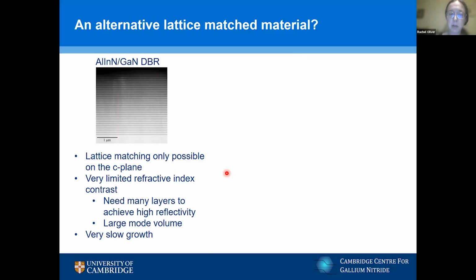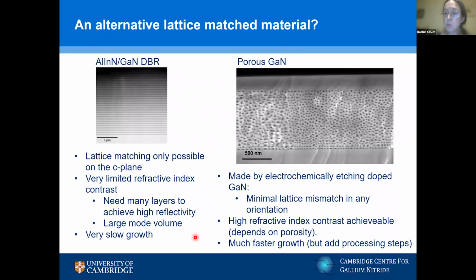The other problem with aluminium indium nitride, gallium nitride, is that there's not much refractive index contrast between those two materials. So you need a huge number of layers to get a high reflectivity. Also, the growth of aluminium indium nitride is really slow to get high quality material. The thing we swapped to was working with porous gallium nitride. Here we're using an electrochemical etching of doped gallium nitride to create porosity in the material. And the pores, basically adding air as a kind of gallium nitride air composite, lower the refractive index. Doped GaN and GaN have hardly any lattice mismatch, so we can get rid of all these strain effects we were worrying about in aluminium indium nitride, gallium nitride. And because the refractive index decreases with the porosity increase, if we've got a high porosity, we can get a very high refractive index contrast.